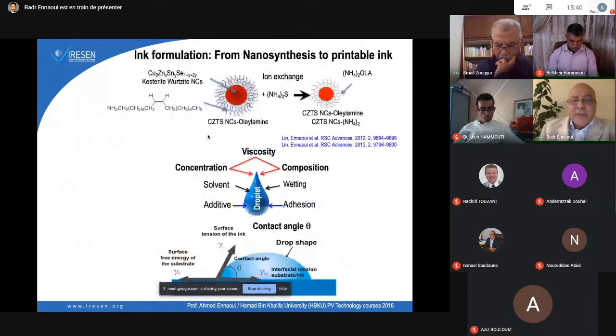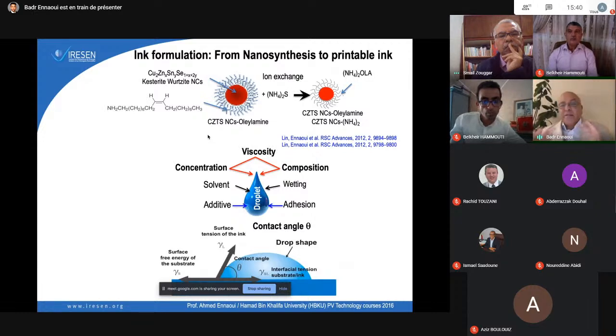So we continue our work with ink formulation by using what we call ion exchange. So when we prepare a material which contains a lot of carbon, we try to use another additive to exchange the ion and take out all this carbon from the solution in order to get a better nanoparticle. We did this. I have here two references from us. You can see them, and you see that